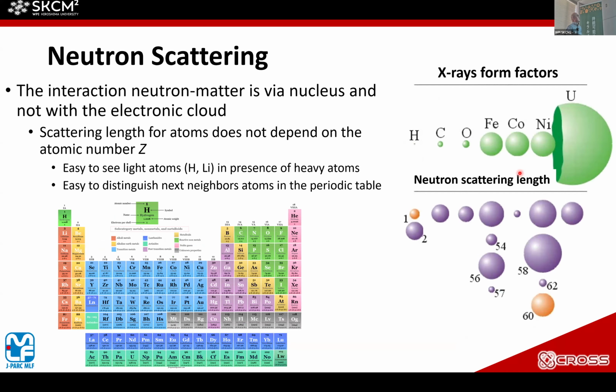And one more feature: the interaction of neutrons with matter is via the nucleus and not with the electron cloud. So compared with X-rays, the scattering length of an atom does not depend on the atomic number. For example, in the X-ray case, the scattering cross section is proportional to the atomic number, but for neutrons, it isn't. So we can detect hydrogen and also its isotope deuterium, and it's easy to see light atoms, for example hydrogen and lithium in the presence of heavy atoms. And it's also easy to distinguish neighboring atoms in the periodic table, for example iron, cobalt, nickel. In the case of X-rays, it's not easy to distinguish these samples, but for neutrons, it's very easy.